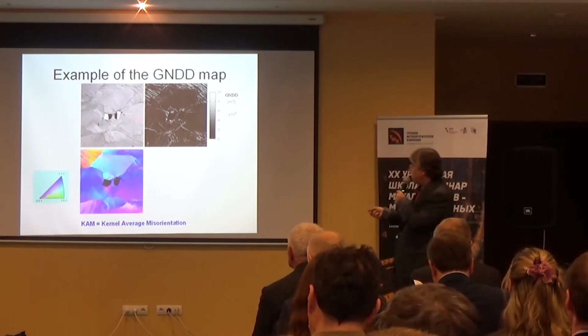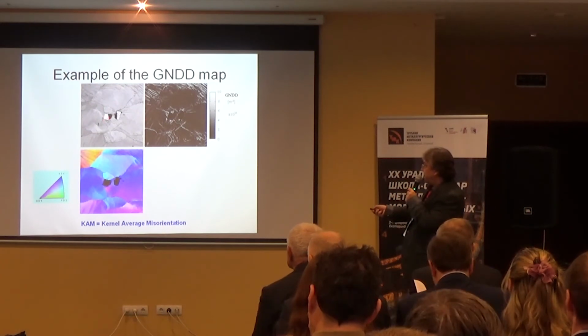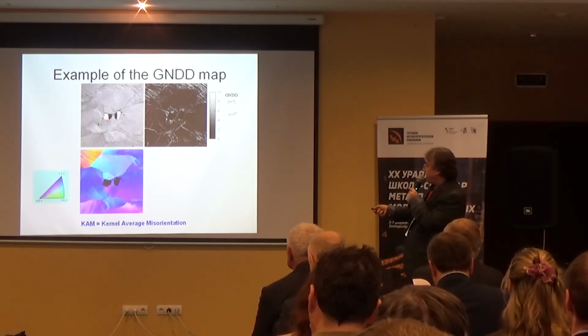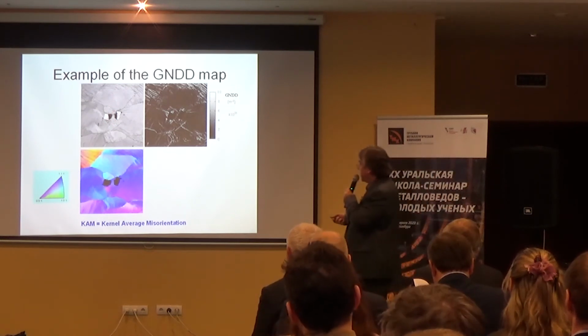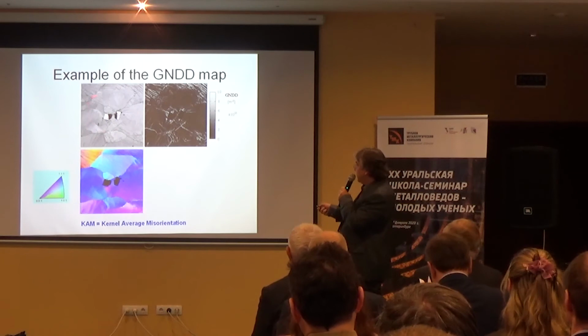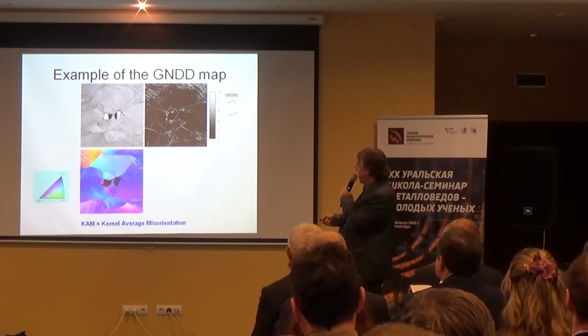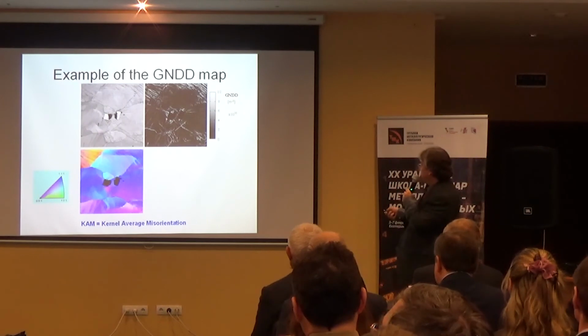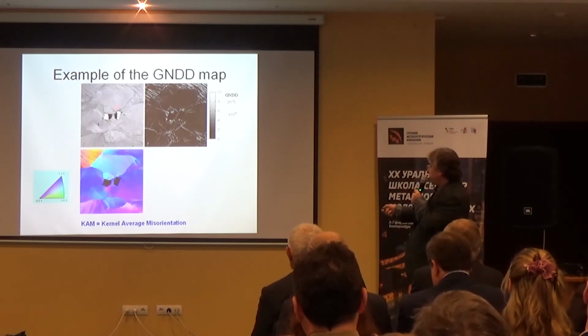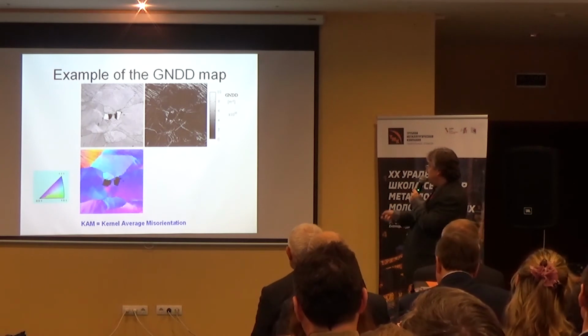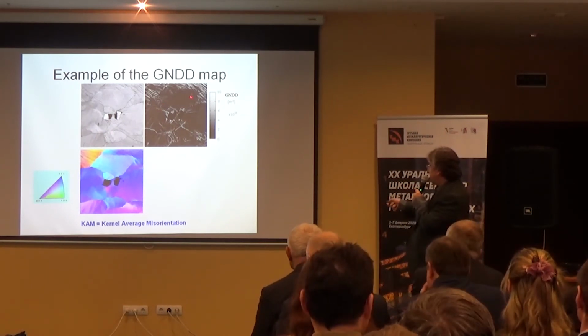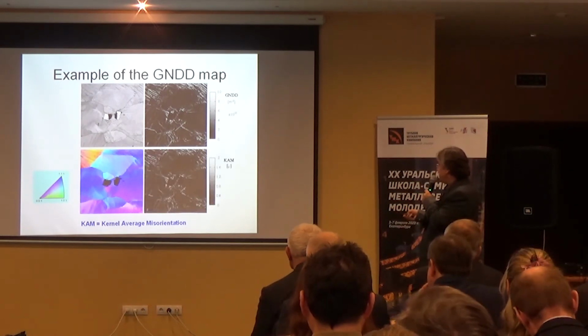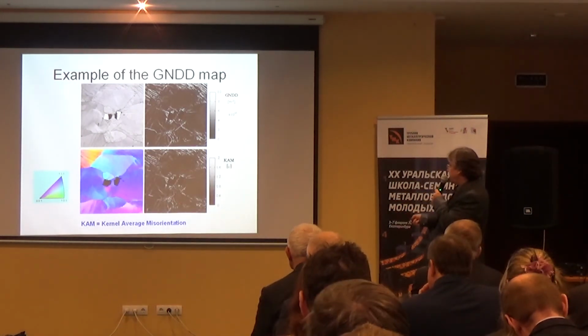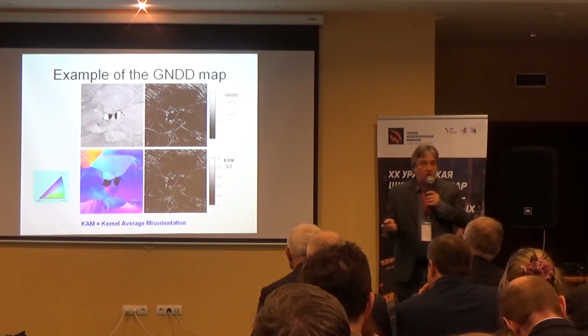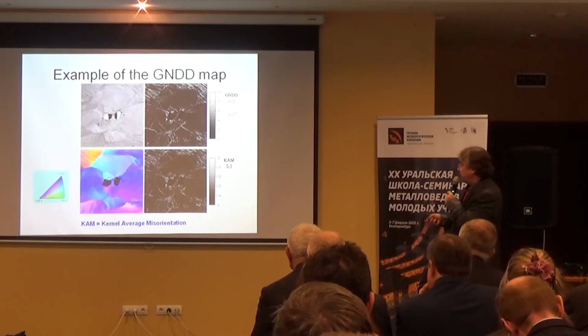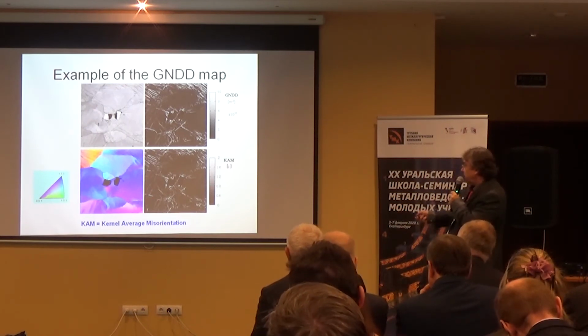So here we worked out a model for that. For example, this is an IF steel, and this is titanium carbide and titanium nitrides. And you can see that this is slightly deformed, and in the vicinity of these particles you have strain increase. So this is the microstructure, this is the crystal orientation, and also the density of geometrically necessary dislocations. Now this is a map, the kernel average misorientation map. It's also extracted from orientation data. It's calculated on the orientation scan.